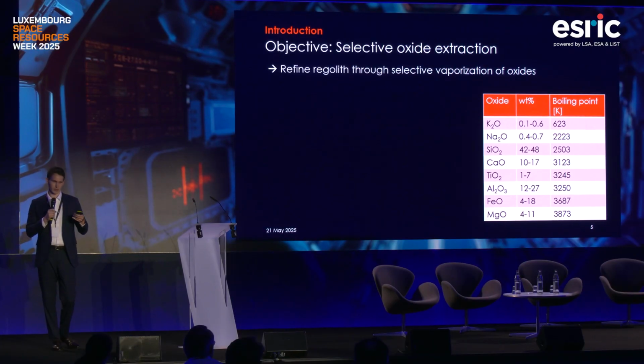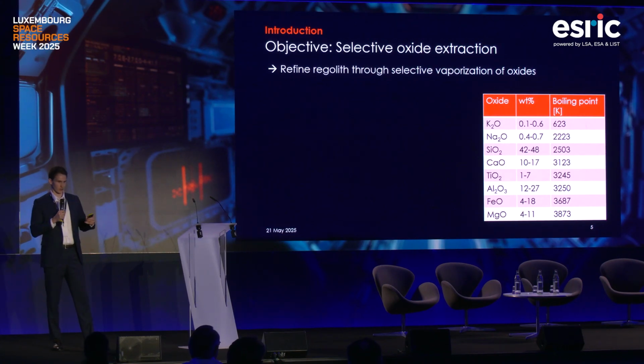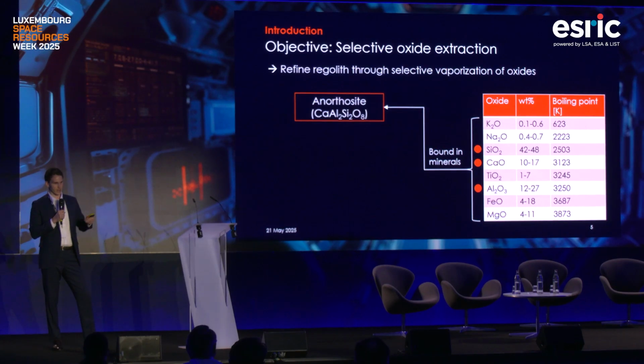And what we can do with this process would be to extract oxides that we have present in the regolith, as we can see here on the table, selectively through boiling. So simply by raising the temperature of the regolith, it's a very simplified approach, we extract the oxide through boiling. And if we simplify this now, taking a look at only anorthosite, so this is the table.